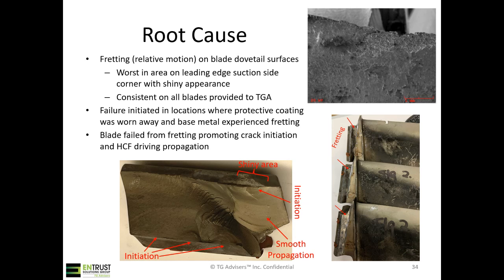So being that this alloy is highly susceptible to fretting and the reduced material properties as a result of fretting, the OEMs are aware of this. They apply protective coatings on these dovetail surfaces to try and minimize the impact of fretting if any sort of relative motion does occur. In normal operation, that coating should be enough to allow these blades to last for an appropriate period of time, or for their design life.